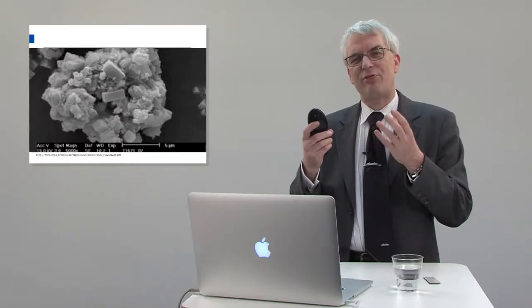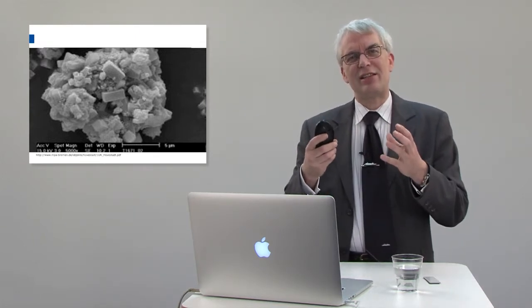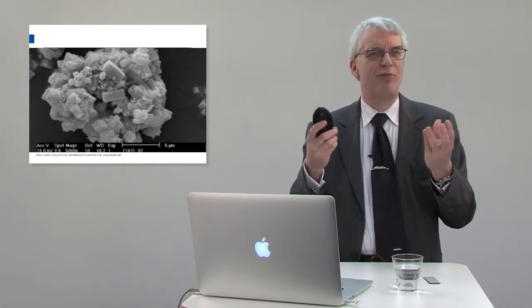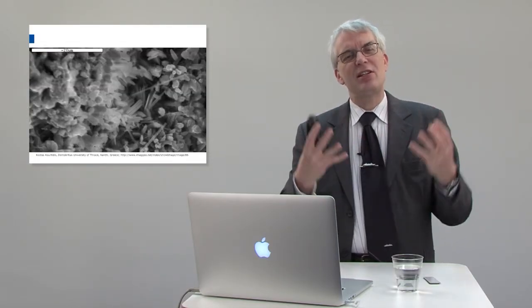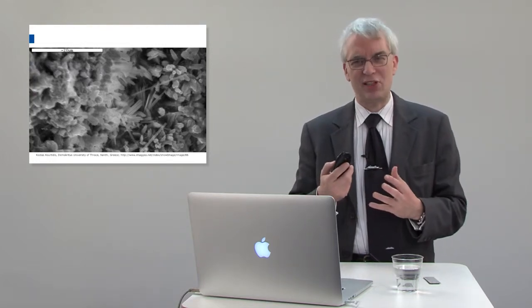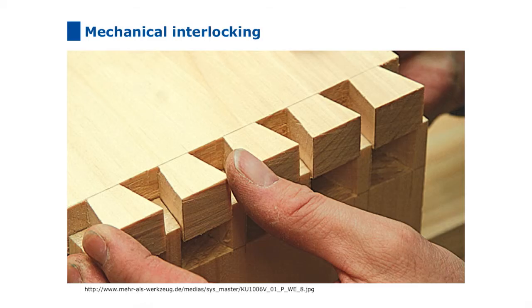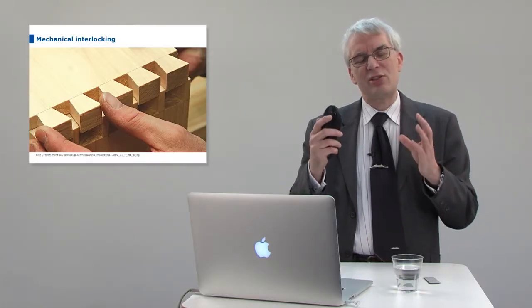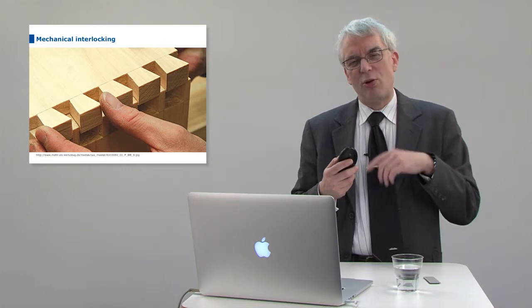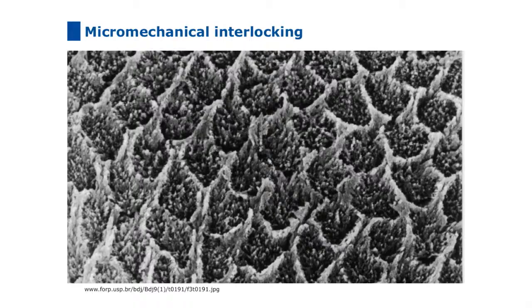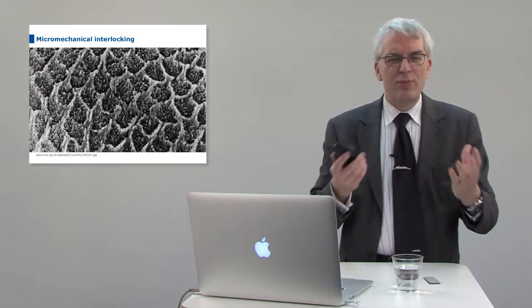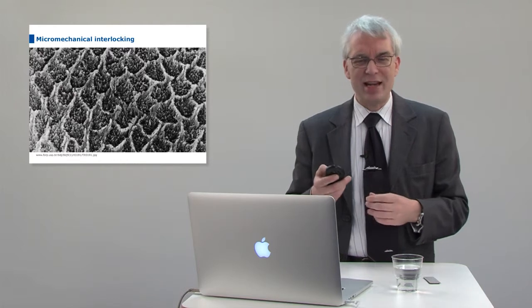Salt not in the sense of table salt, which is very soluble in water, but salt in the sense of a compound like gypsum, for example. And these crystals that are formed in this salt, they can interlock with any surface, and they will interlock with each other. And this interlocking is the basic curing and setting reaction of the cement. And even though this may seem a bit crude, micromechanical interlocking is quite a strong force and can hold things really well together. But it also works on a lower level, like when we etch enamel and we put a bonding agent on this etched surface, then these cured resin parts interlock with this surface, and this is quite a strong bond. So micromechanical interlocking is also a driving force in cements.